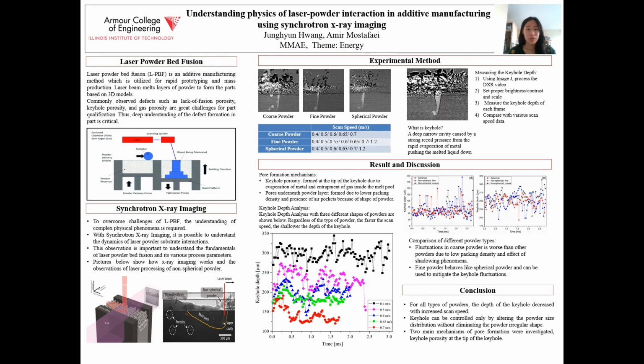Three types of powders were used in the experiment: coarse powder, fine powder, and spherical powders. Different scan speed of laser from 0.4 meter per second to 1.2 meter per second went through the powders with same laser power. From the X-ray imaging, we could understand the pore formation mechanisms.